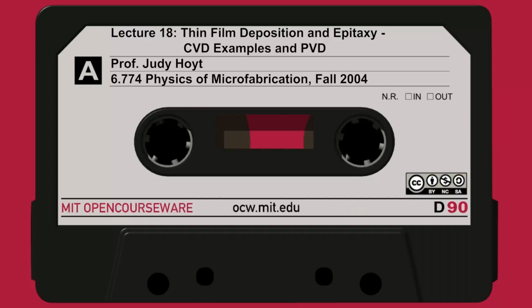So here's just an example of a cross-section TEM of an undoped film. It's a little hard to see, it didn't reproduce that well, but you see the very columnar grain structure. These dark bands correspond to regions where the electron beam is diffracted by the different crystalline orientations and by grain boundaries. So an undoped film deposited at 625, in cross-section, looks something like this, a very columnar grain structure with relatively small grain size.